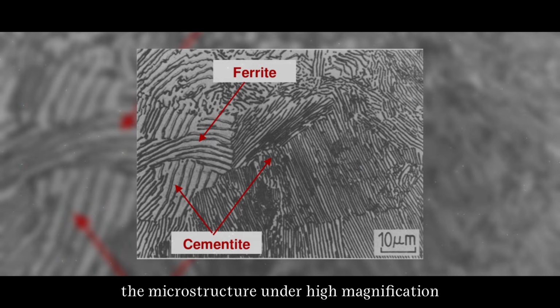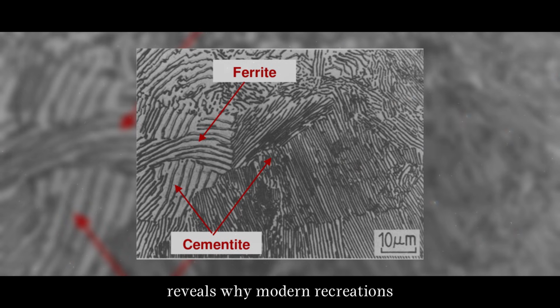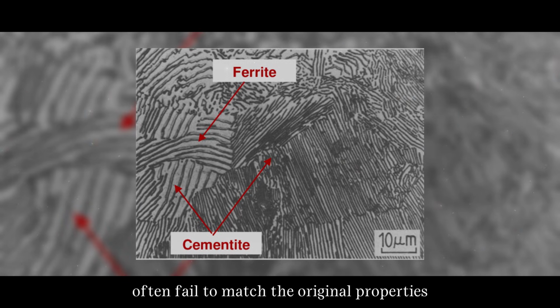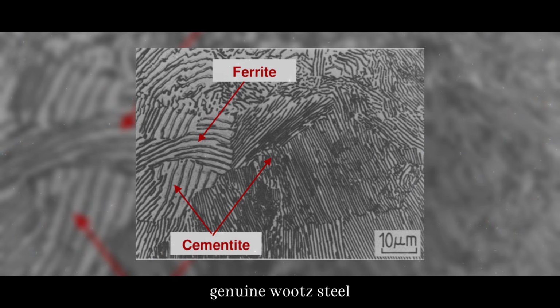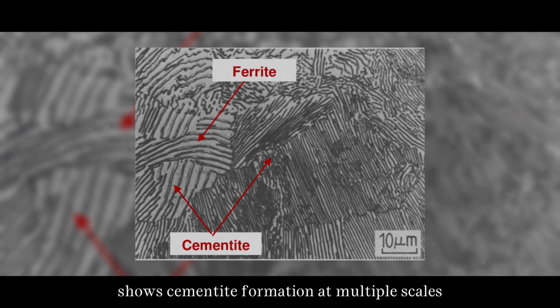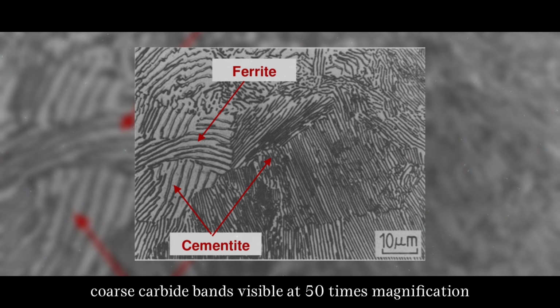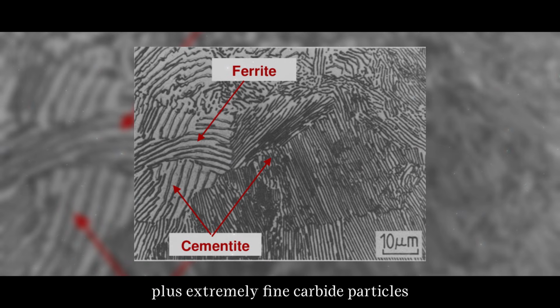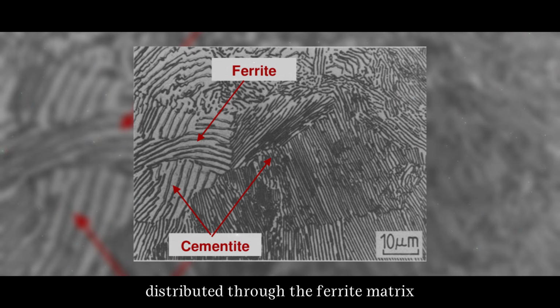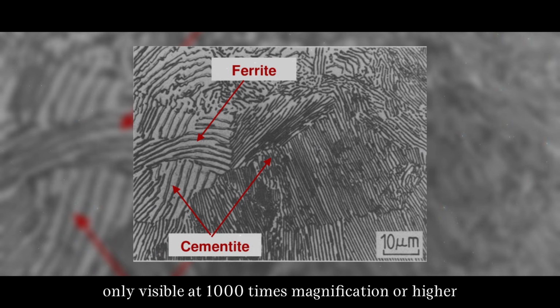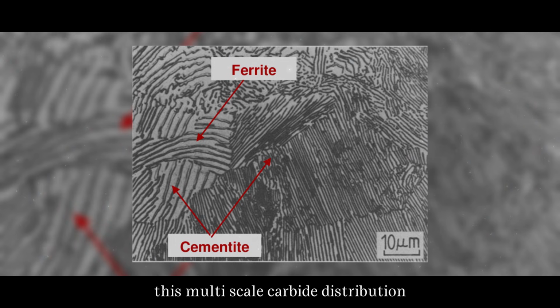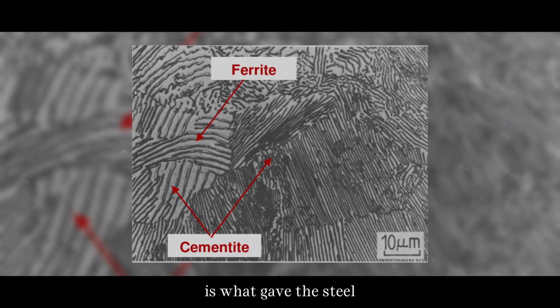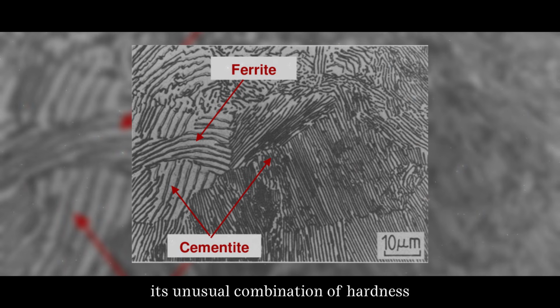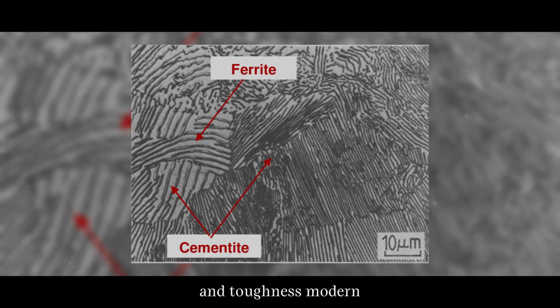The microstructure under high magnification reveals why modern recreations often fail to match the original properties. Genuine wootz steel shows cementite formation at multiple scales: coarse carbide bands visible at 50 times magnification, plus extremely fine carbide particles distributed through the ferrite matrix, only visible at 1,000 times magnification or higher. This multi-scale carbide distribution is what gave the steel its unusual combination of hardness and toughness.